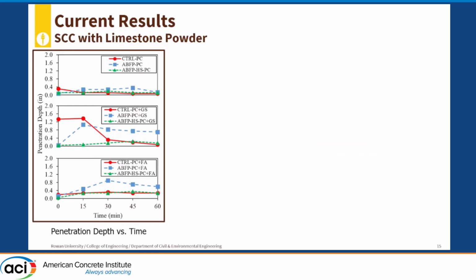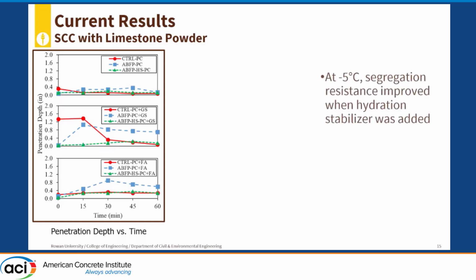This is the penetration depth versus time, or a measure of segregation resistance. So our observation here is that mixtures with hydration stabilizer, or the green ones, have less penetration depth, or more segregation resistance, compared to the ones without hydration stabilizer. So we can say that with more workable mixtures, they may have less segregation resistance.